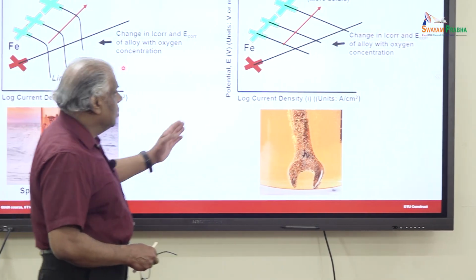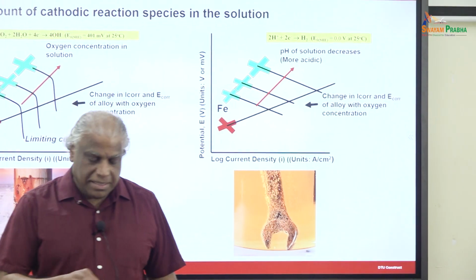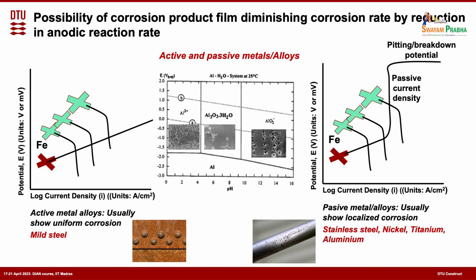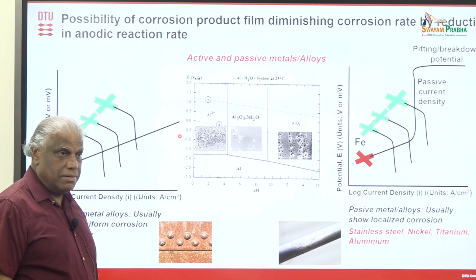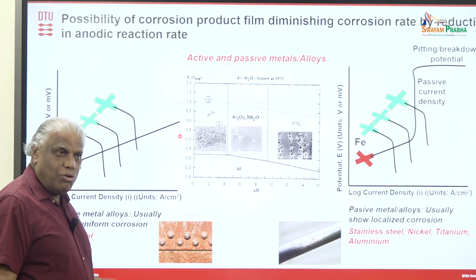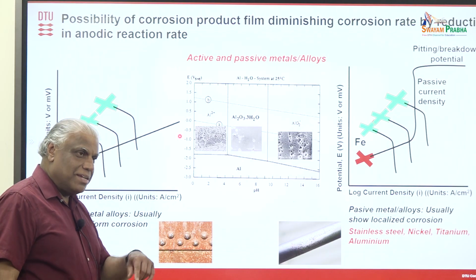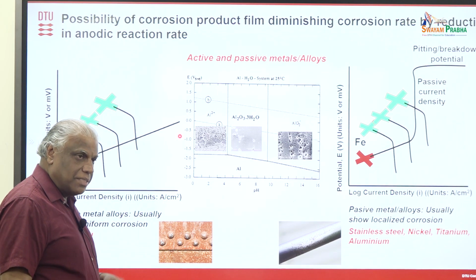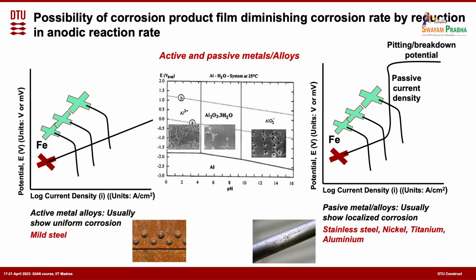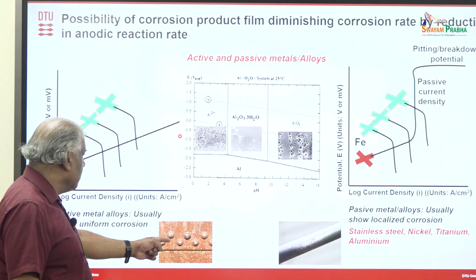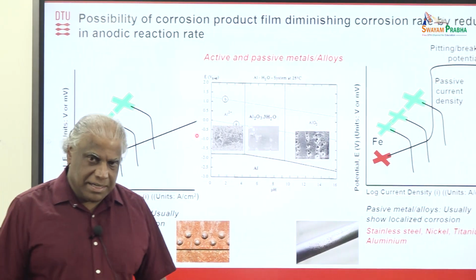As I mentioned, this will not happen in the hydrogen case, because hydrogen is easily migrating. It depends upon whether it is bad or good, and whether you have an active metal or passive metal, for example. So here you can see that when you are increasing the oxygen concentration, or if you are agitating, or if you are increasing temperature, because of this limiting current shift, it is not good in this case, right? As the oxygen concentration is increasing, it is not good because the corrosion rate of this active metal is increasing, right?